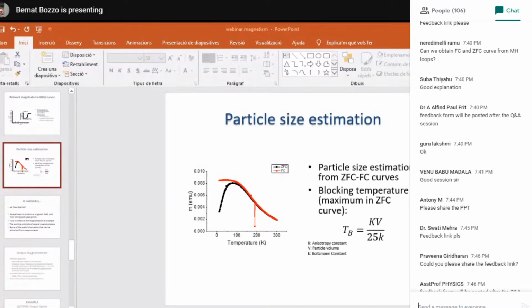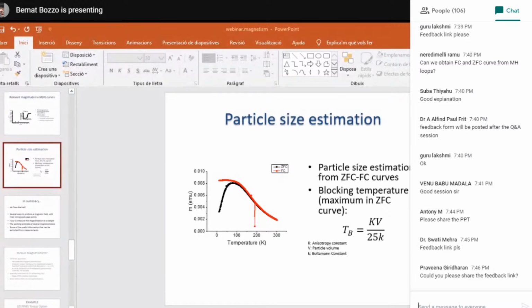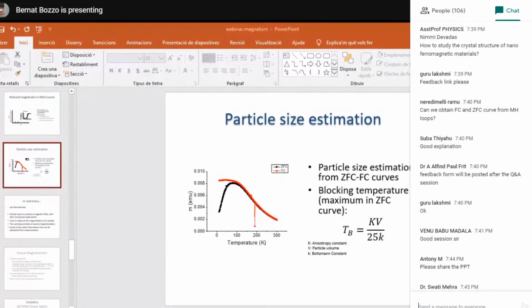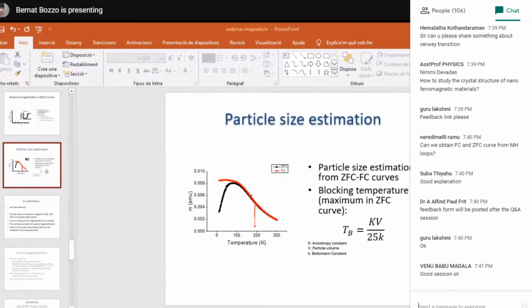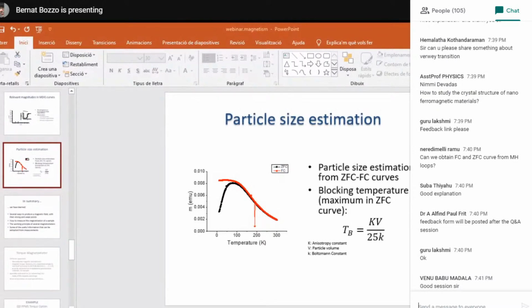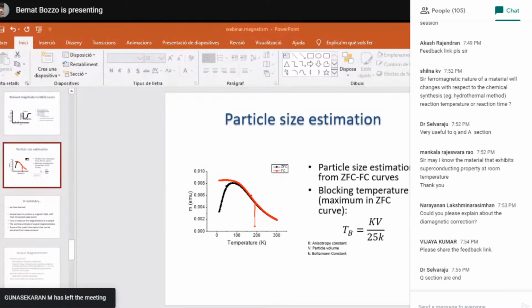Regarding room temperature conductivity, the answer is no. There is no such conductive material at room temperature. So far, any claim that has appeared is proven to be caused by some kind of measurement artifact. It is very important to know the measurement artifacts, because they can lead you to false conclusions, especially if you are dealing with very low magnetic signal measurements. Sometimes any impurity in your holder or any poorly centered or unprotected sample can lead you to very funny results. Spurious signals have to be taken very seriously. And I think there are no more questions.